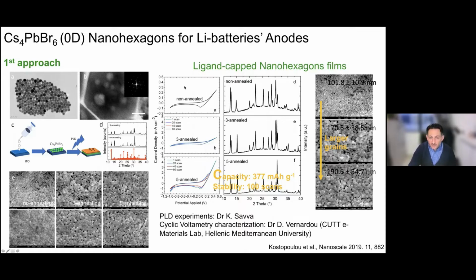We then measured the electrochemical performance of these layers against silver chloride electrodes. You can see that in the non-annealed case we see practically no electrochemical activity in the cyclic voltammetry experiments. By the way, the cyclic voltammetry characterization was done by Dr. Vernardou at the Hellenic Mediterranean University. But when one anneals and you get larger grains, one can see electrochemical performance, and in the 5 annealed case you can reach a capacity of 377 milliampere-hours per gram. This is repeatable and can last up to 100 scans, and then the cell degrades, possibly because of degradation of the passivation layer.